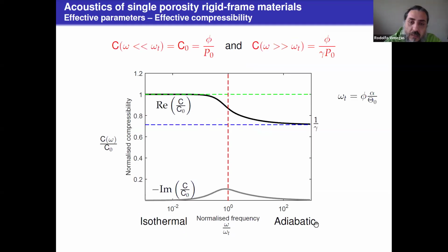In this regime, we say that inertia is dominating the fluid flow in the material. Similarly, for the compressibility, we scale it by the isothermal value, which is the porosity over the equilibrium pressure. It will tend to 1. There is a transition region determined by this thermal characteristic frequency. And at high frequencies, we say that the propagation of sound will be adiabatic and the compressibility will become real, and in its normalized version, it will tend to 1 over the adiabatic exponent, or specific heat capacity ratio. So those are the properties of a conventional porous material.